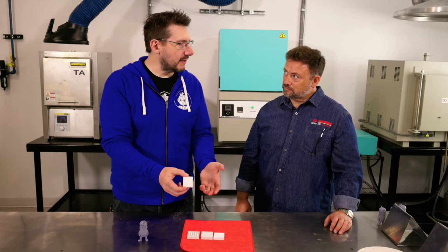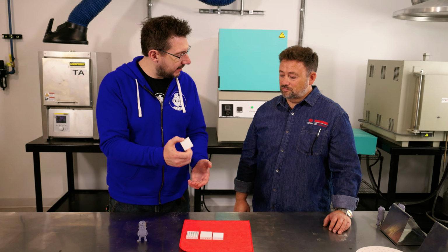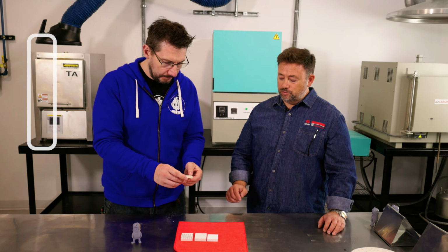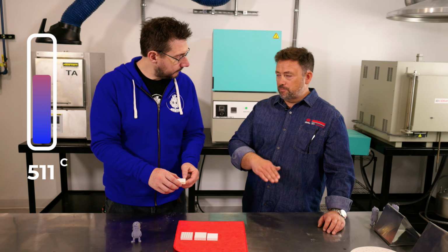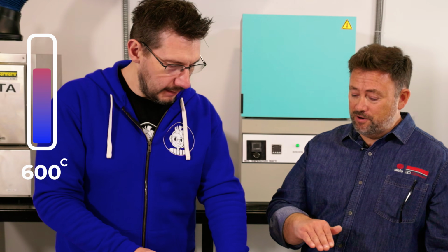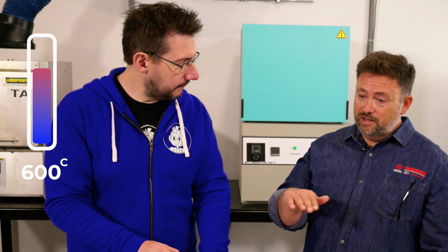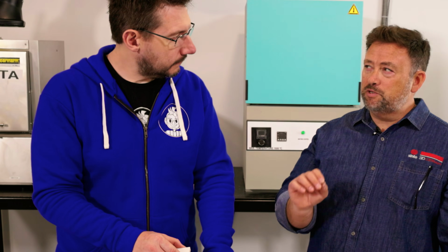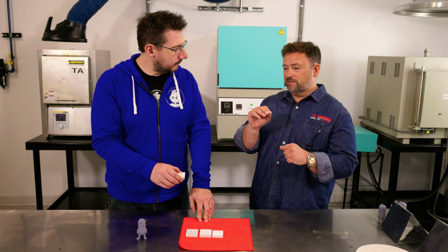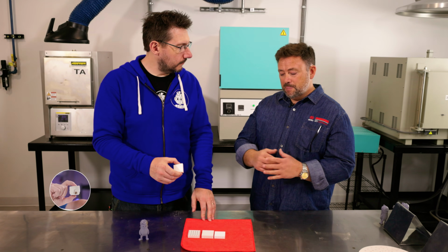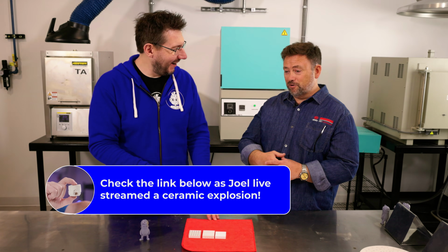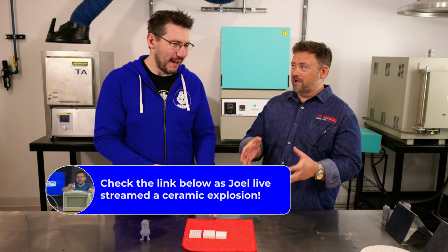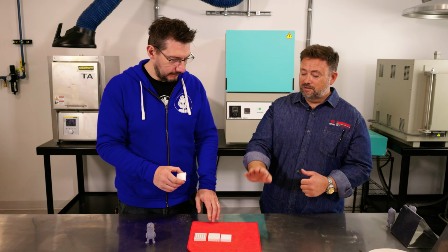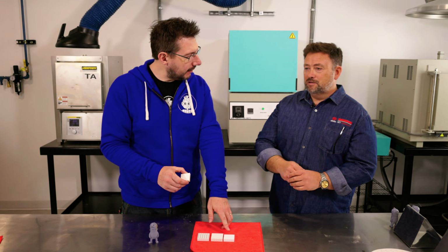Now, when we talk about sintering, what temperature does this have to exist at? And what's the timetable for that? Right, so to debind, it's a very slow ramp up to about 600 C to burn off that resin. That's this one right here, debinding. Right, and you stay at 600 C, but that ramp has to be very slow because if you heat too fast, again, the ceramic can crack. I'm sure if anyone has ever fired a piece of pottery and you fired it too fast, it cracks. And then all your work to make this beautiful shape is gone. So we're shaping it and forming it, we're cleaning it, then we're debinding it. But how slow? Like an hour?